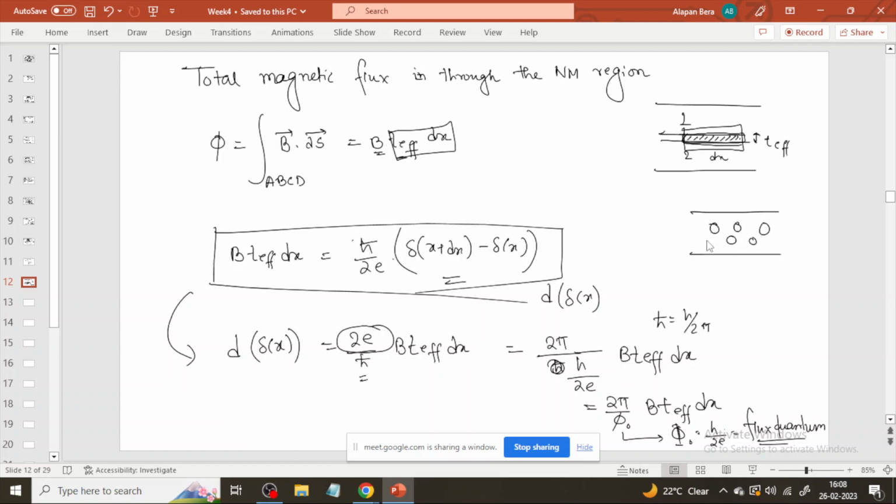So if we consider some vortices inside a superconductor, and we apply a magnetic field from outside, then the magnetic flux that each vortex can contain is given by some integer number n times this flux quantum. So the magnetic flux that can pass through these vortices is not arbitrary; it is quantized.